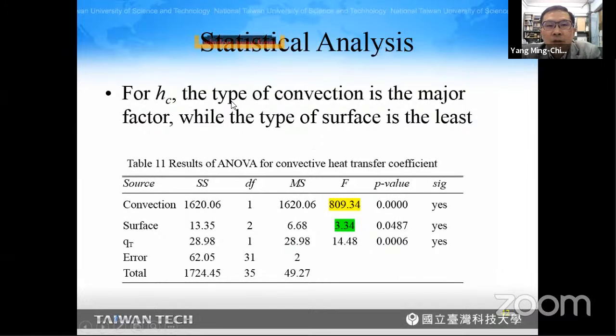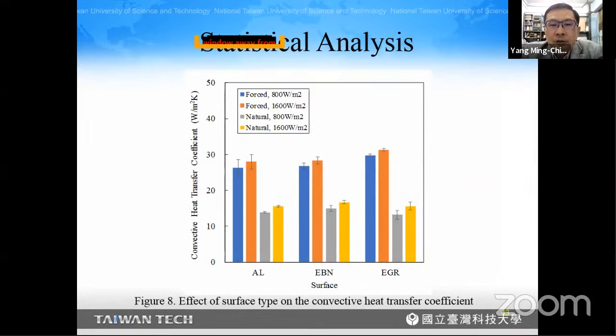And for convective heat transfer, the type of convection is the major factor. Here, the convection shows that the type of convection is the major factor, and the surface type is the least. That is, in the case of convective heat transfer, whether the surface is coated or not is not an important factor. And this figure shows that the difference between the coating is not as big as in the case of total heat transfer.